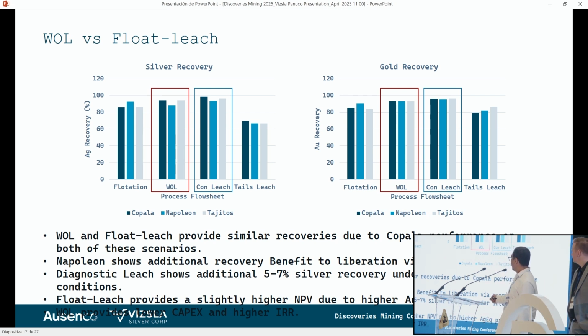Sorry, I forgot to mention that the diagnostic leach on the Napoleon deposit shows that we can get around a 5 to 7% recovery increase if we have regrind. Instead of having a 70 micron grind size, we reduce it to 20 micron, and we have a 5 to 7% increase in recovery. So this is why the float leaching circuit was selected for the second phase of the project, instead of just going whole ore leach the whole way.